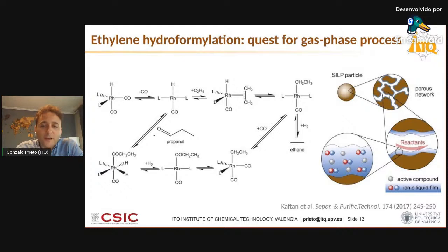What is the problem of solid catalysts? Because there has been research on all solid, all inorganic catalysts for ethylene hydroformylation in the gas phase for decades and decades. But the major problem is that in all cases, they also trigger to some extent this undesired ethylene hydrogenation to ethane as a side product. So that's one of the long-standing challenges with solid catalysts. And that was the reason why they traditionally could not match performance of those molecular counterparts in liquid media.